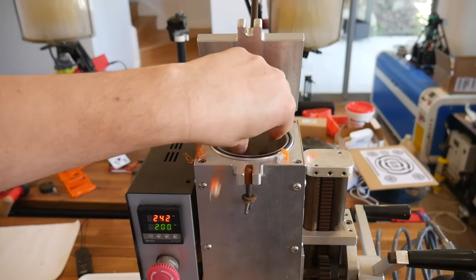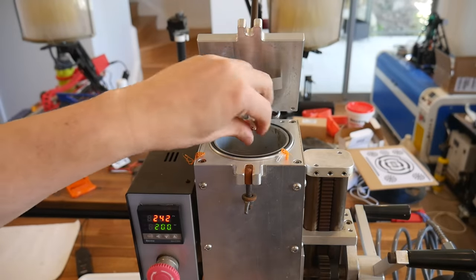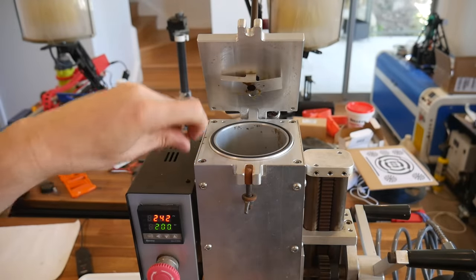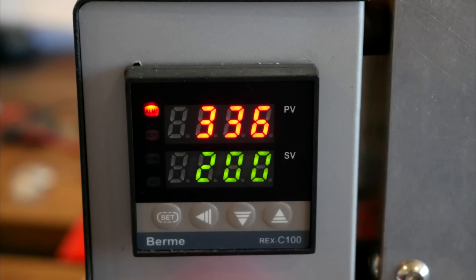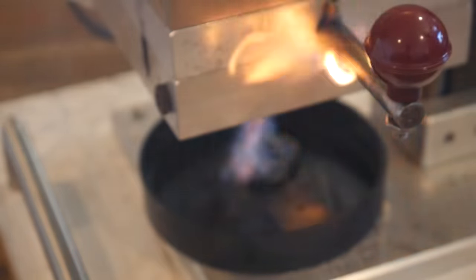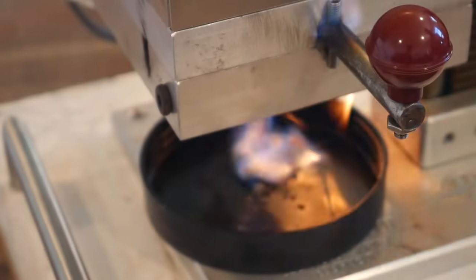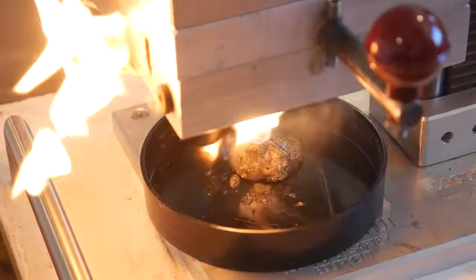So I put everything back together, turned on the heater, set it to 200, and started to load some waste plastic. But you can already see a problem in the making. The temperature was overshooting by a ridiculous amount, and PID auto-tune did not work like the manual said it would. The plastic coming out was a charred mess, and I even managed to set it on fire at one stage. This clip pretty much sums up how the whole process was going.